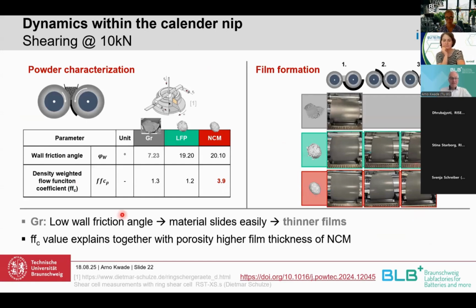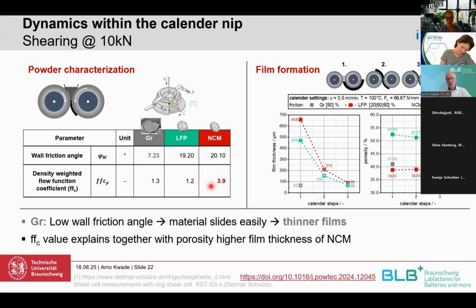By the ring shear cell, you see that the wall friction angle is by far the lowest for the graphite. That also helps us to get the right film thickness after only one pass through the calendering gap. But for the other two cathode materials, we need 3 passes to come to the right thickness, and by that areal weight. And what you can also see is that NCM has, let's say, better flowability. That makes it even more difficult to come to the good film thickness, because then more powder is flowing into the gap, so that we need higher calendering pressures to come down.